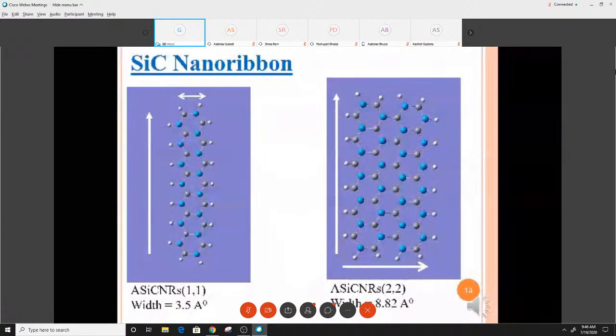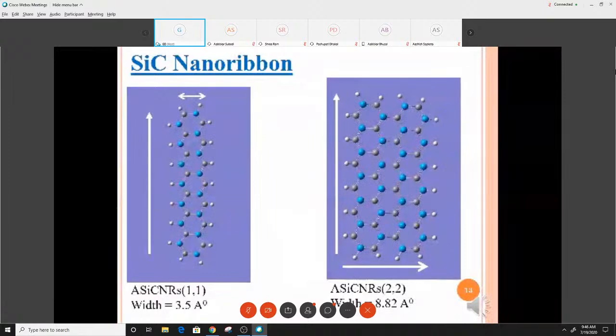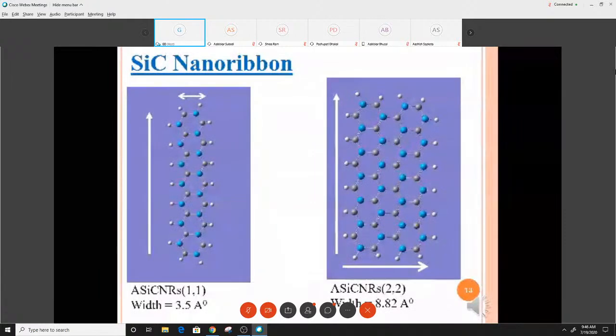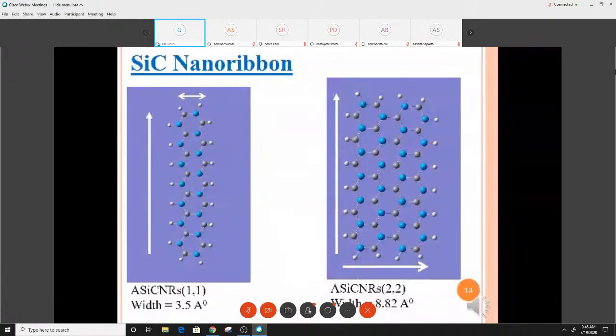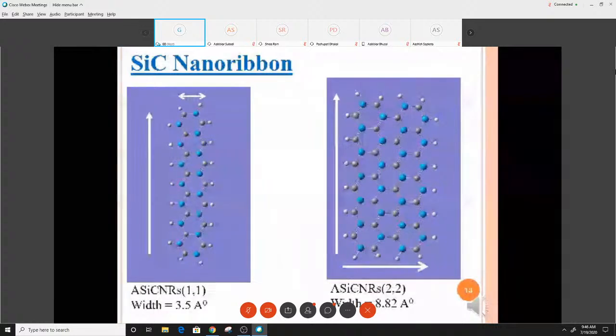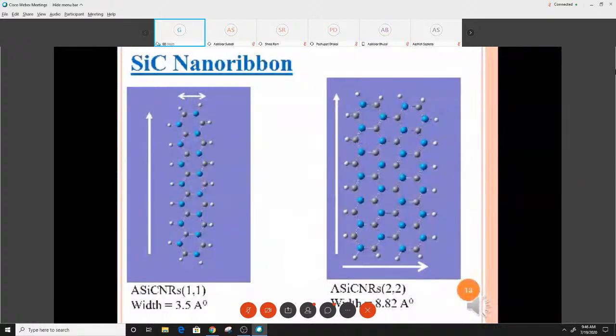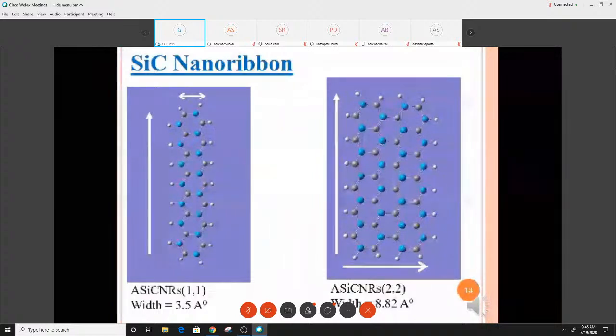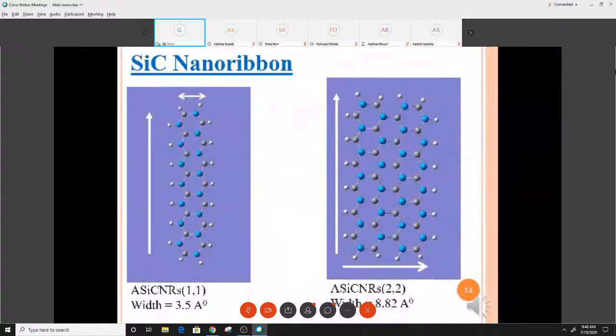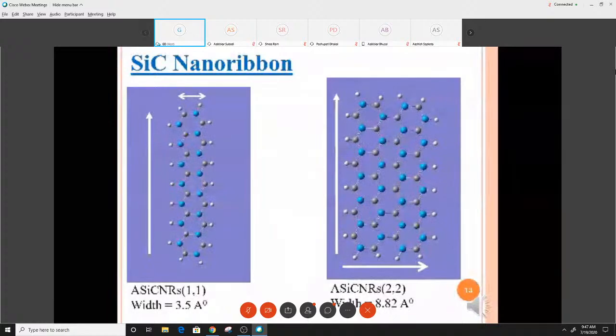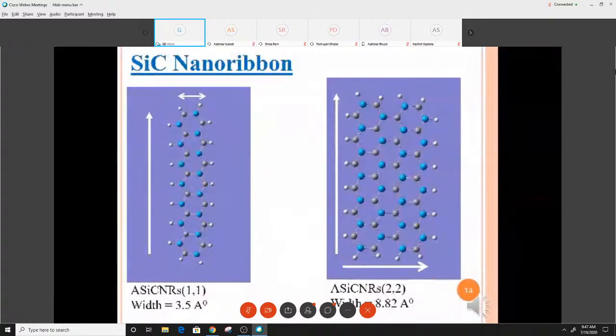silicon carbide nanoribbon. Here the figure shows silicon carbide nanoribbons. The first one is the 1 armchair silicon carbide nanoribbon having width 3.5 angstrom, and the second one is the 2 armchair silicon carbide nanoribbon having width 8.82 angstrom. 1 and 2 are the chiral vectors that define the size of each nanoribbon. Most calculations were done on the 1 nanoribbon. For the 2 nanoribbon, we just optimize and compare each structure.